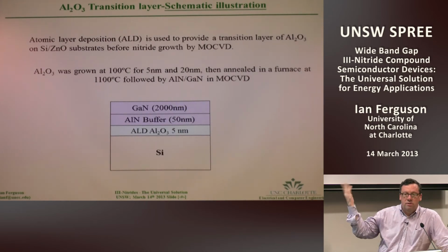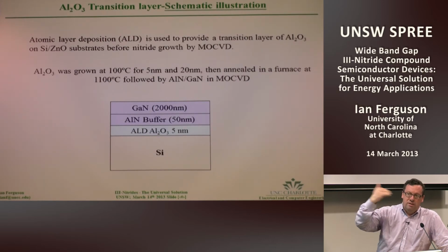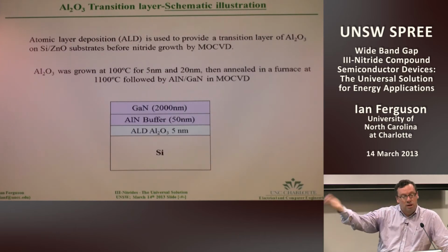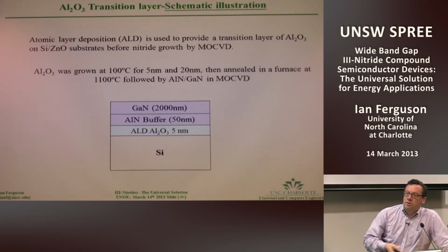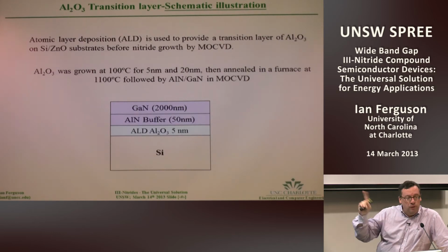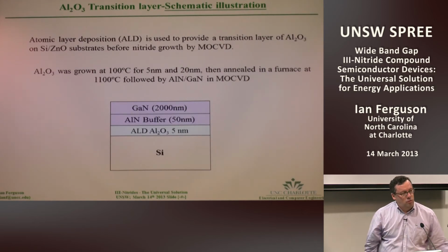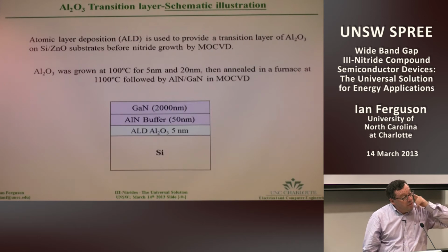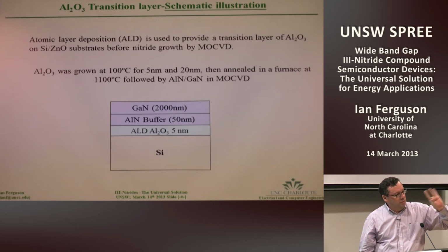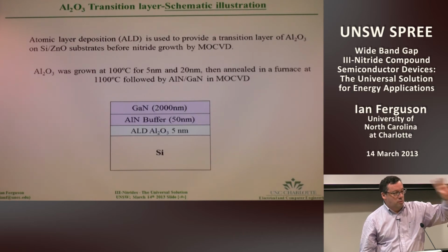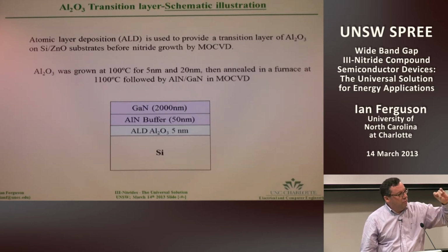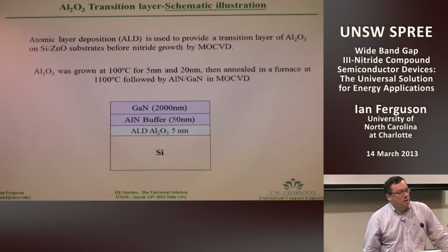I put this up because I know there's a number of people here who are looking at how you take silicon and modify it to enhance its behavior as, for example, a solar cell. It's a difficult problem because with silicon, you're dealing with a polar, nonpolar surface. You then have to deal with some type of transition layer between the silicon and the 3-5 material. The general issue of growing a compound semiconductor or 3-5 on silicon as a whole is a hard problem.